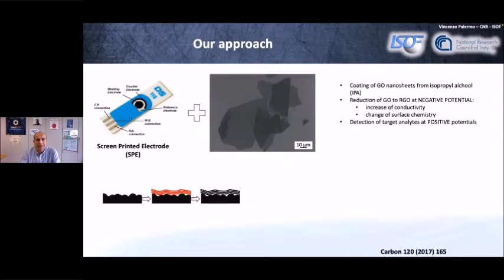Usually these sensors are made of conductive inks made of silver, but also carbon, whose surface is a bit disordered and not really controlled. So what we did was to take our graphene, or in this case graphene oxide, coat it on this substrate, and we can either keep it as it is, so the soluble version, or we can reduce it electrochemically so that we go partially back to graphene, so we can really tune the amount of defects that are there.